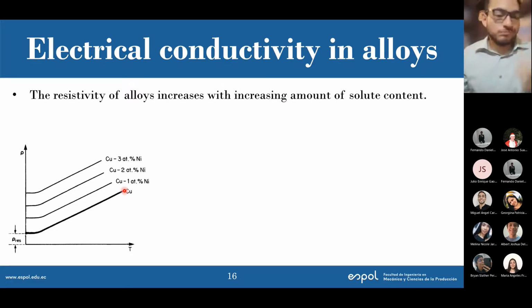That's actually putting other elements, you can call it alloying, for example in semiconductors, so you can increase the conductivity and obviously reduce the resistivity. But we're talking about metals here, and in metals, especially metals that have high conductivity by themselves, if I put in any alloy element, in general, most of them will cause the resistivity to go higher and therefore the conductivity to go lower.